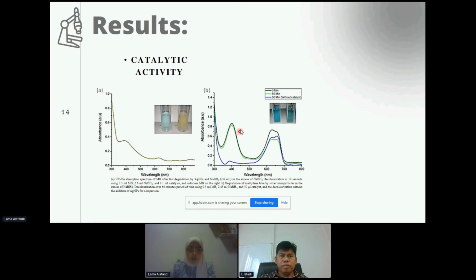Here we notice another peak, and we assume this is because of the interaction and reaction between sodium borohydride, which we added to reduce methylene blue, and the catalyst, which caused more reduction of silver nanoparticles, as we can see here at a wavelength of 400, which is the same as before, where we saw the formation of silver nanoparticles at this wavelength.